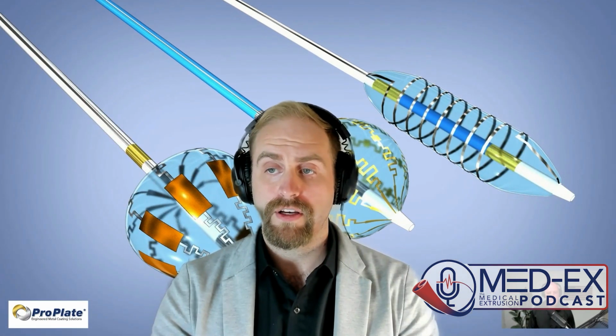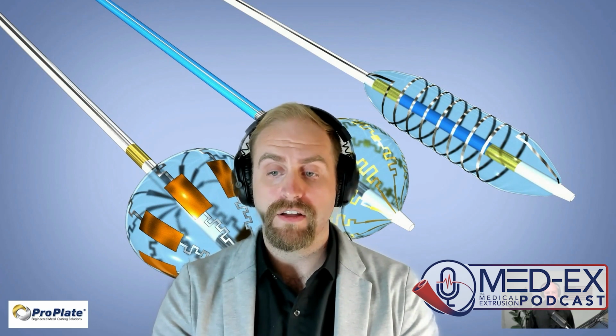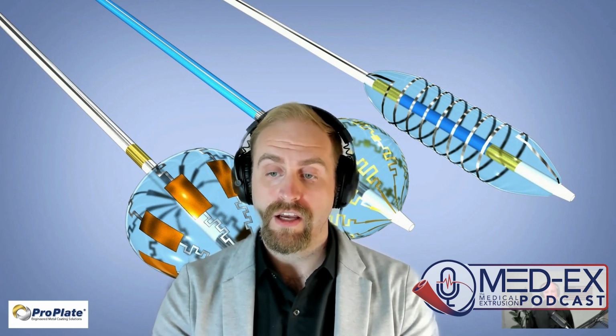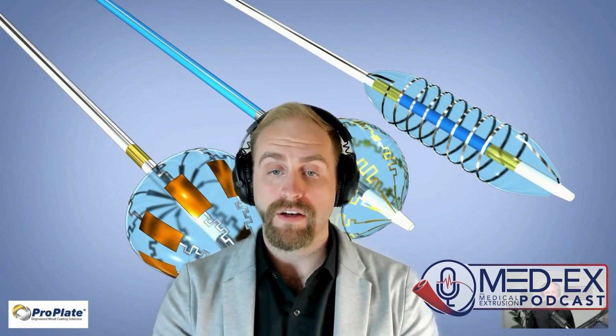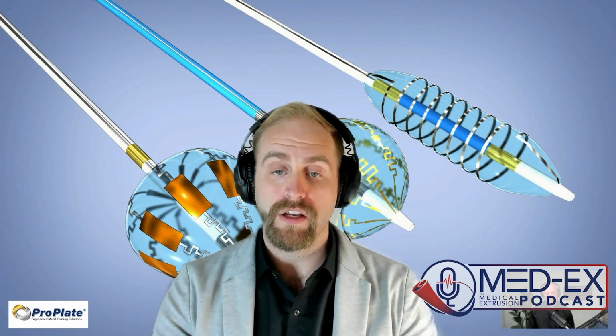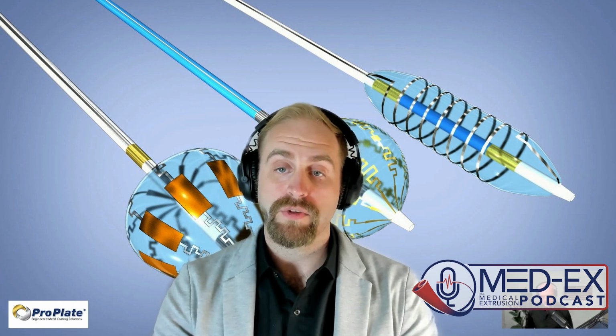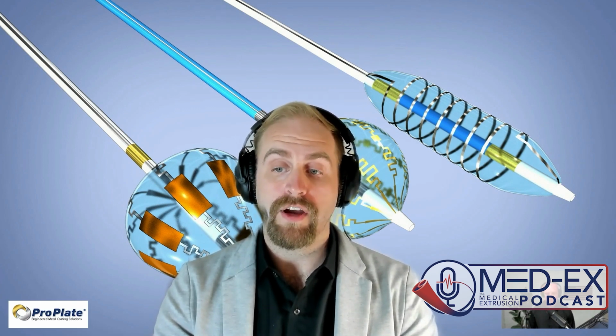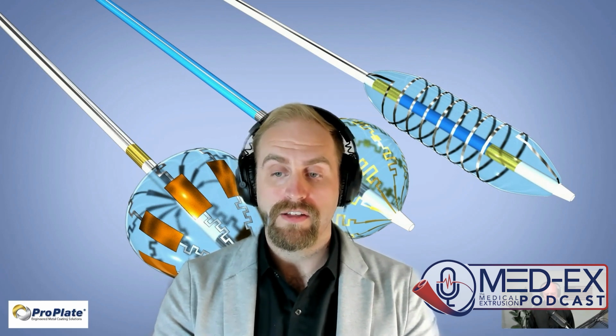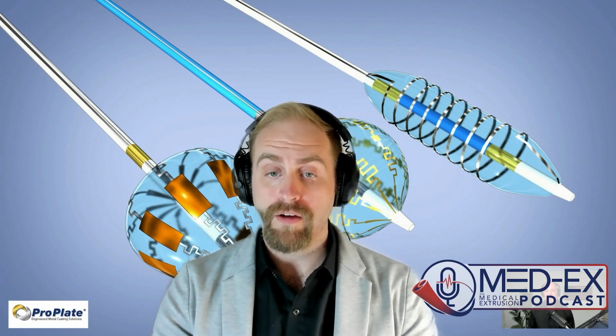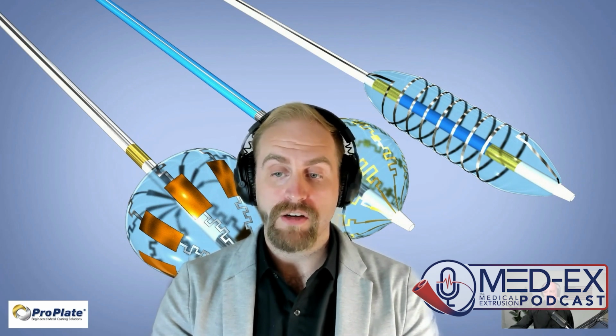Certainly. So with nitinol, well, plating will create hydrogen. And we don't want hydrogen to be embedded into the plating or the part itself, especially with nitinol. That can cause embrittlement. So there's a series of steps that we can take in the plating process to help reduce the amount of hydrogen that's created. But you can't completely eliminate it on the plating side itself. So then afterwards, we can do a low temp bake to relieve the hydrogen as well. And everything is below about 200C or 400F. And so we're not negatively impacting the shape memory properties through thermal energy.